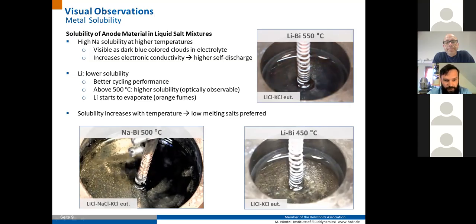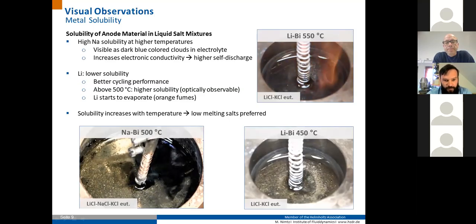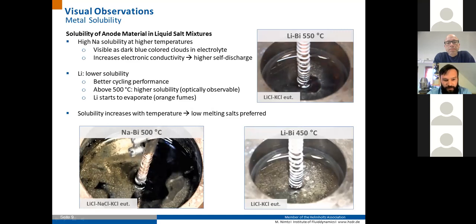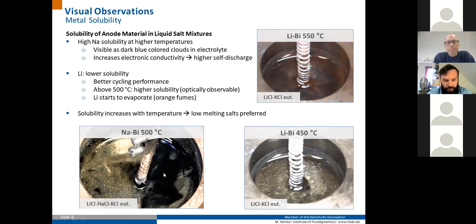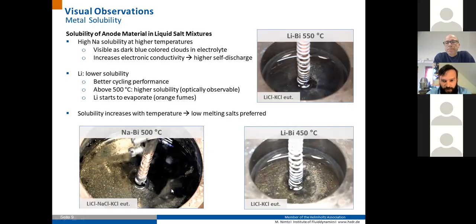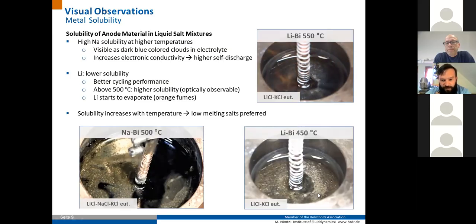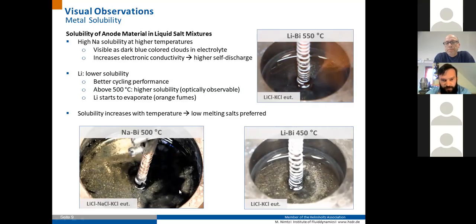And if you observe such a high solubility of a metal in the electrolyte, this typically means the cell will have a high self-discharge rate, as there are free metal atoms available in the electrolyte, which can then react with the lower electrode, bismuth in this case. And this is something to be avoided. For lithium on the lower right, the solubility is much lower. This leads to a much better cycling performance. As you can see, there is some solubility, but it's not as intense as for sodium.